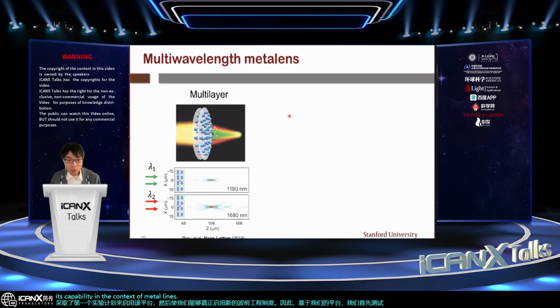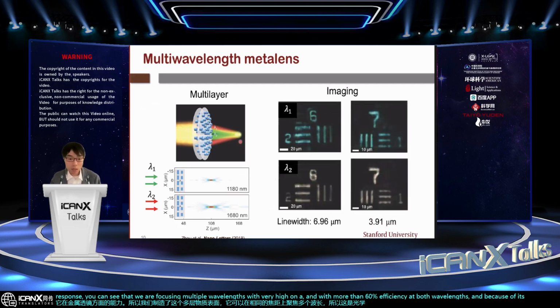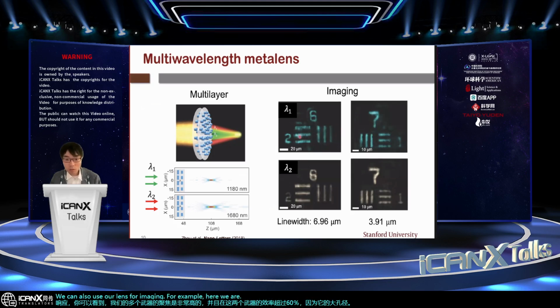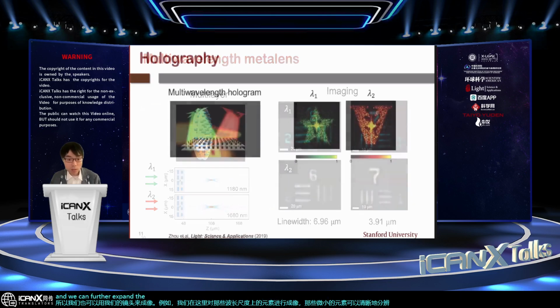We fabricated this multi-layer metasurface, which can focus multiple wavelengths at the same focal distance. So this is the optical response. You can see that we are focusing multiple wavelengths with very high NA and with more than 60% efficiency at both wavelengths. And because of its large numerical aperture, we can also use our lens for imaging. For example, here we are imaging elements on the scale of wavelengths, and those tiny elements can be clearly resolved under both wavelengths. And we can further expand the capability into holography.